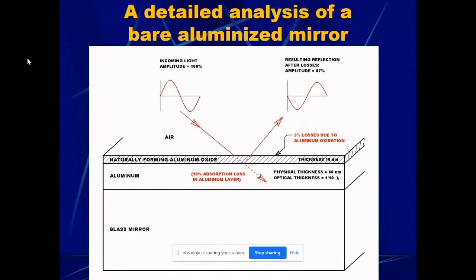Now let's look at how mirrors are done with thin films. Typically an aluminum coating is very, very thin. It's about 600 atoms thick, or 60 nanometers in this case. The problem with aluminum is that in a vacuum, it reflects 90%, but as soon as you introduce it to air, it immediately oxidizes, and you get a 10 nanometer aluminum oxide layer that forms on it. We only get an 87% reflection off the aluminum. Not very good, especially if you have 2 or 3 reflections in your telescope. You would be down to 65% with 3 reflections. So we need to improve the reflectivity of the aluminum.